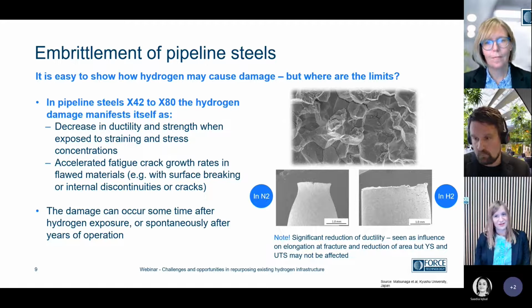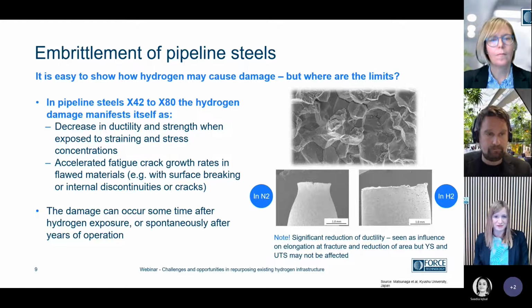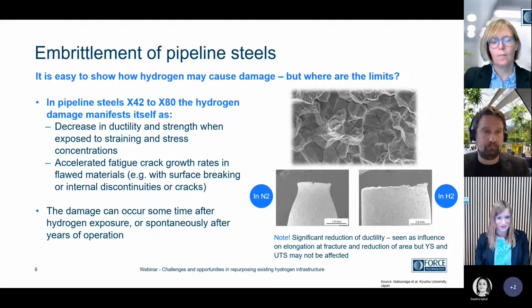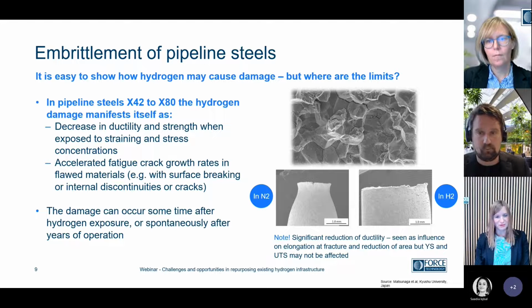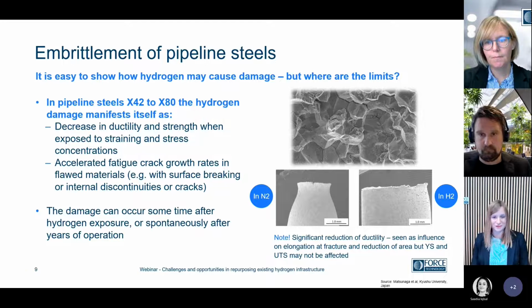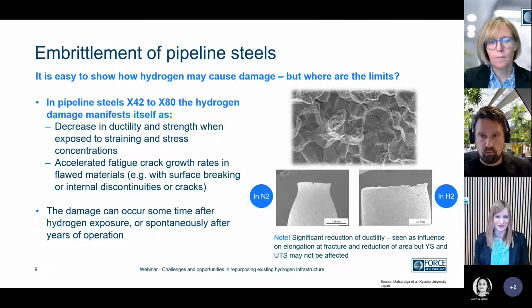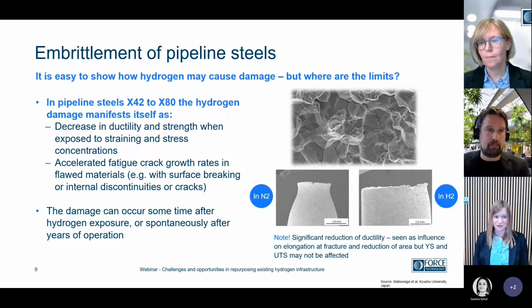And if the conditions of hydrogen embrittlement are met, we can see how it manifests itself in the material. As you can see from this tensile test sample, you would typically in a steel have a ductile behavior with some necking, but if charged in hydrogen, you may experience this brittle behavior as we see to the right. In a scanning electron microscope, the fracture morphology would be this intercrystalline one, typically. And this is what we would see at pipeline steels X42 to X80. And the damage may occur sometime after hydrogen exposure or after years of operation.